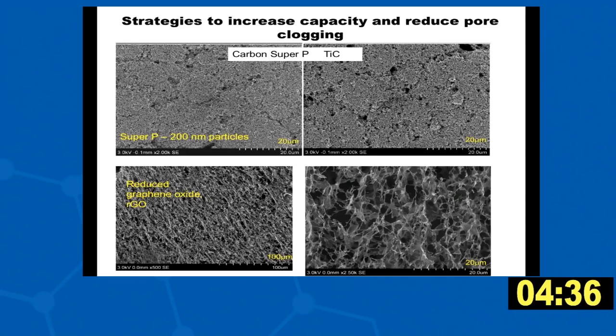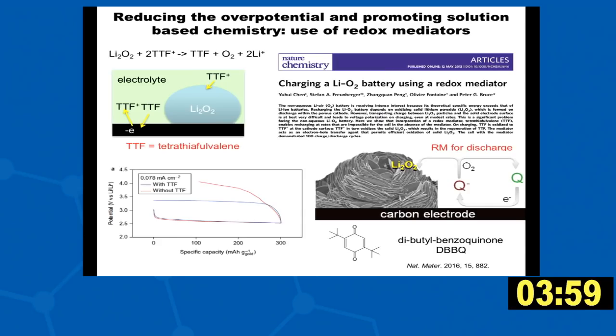And so one of the strategies that we've been looking at is designing graphene-based electrodes in order to reduce pore clogging. So these are the pictures now showing you the Super P particles, 100 to 200 nanometer particles. This is one with titanium carbide, which was proposed by Linda Nazar a number of years ago as a good catalytic structure for this. But again, you can see that all of these electrodes, unless you do a lot of engineering, have very small pores. But if you move to these reduced graphene oxide electrodes, you can get highly porous hierarchical structures, which in principle should allow you to increase rate and capacity in these systems. Okay, so graphene electrodes is one strategy and route forward.